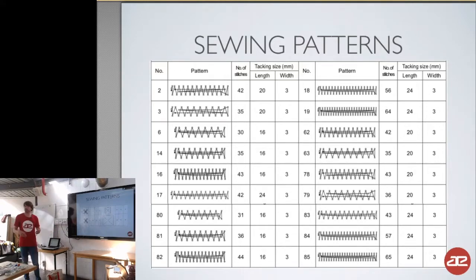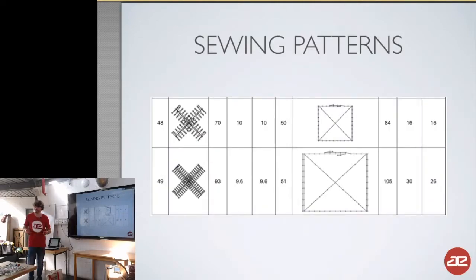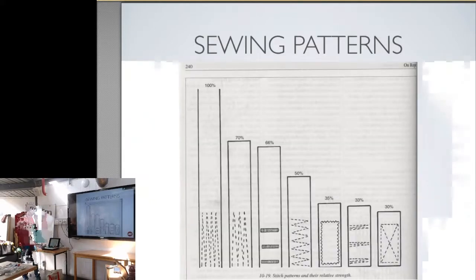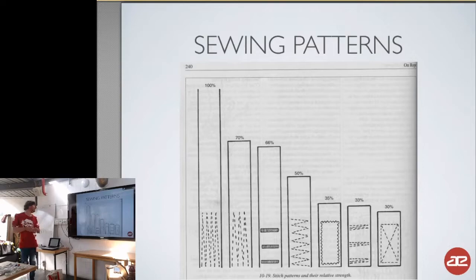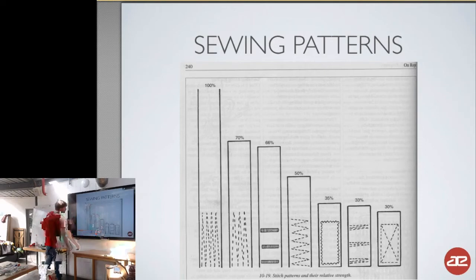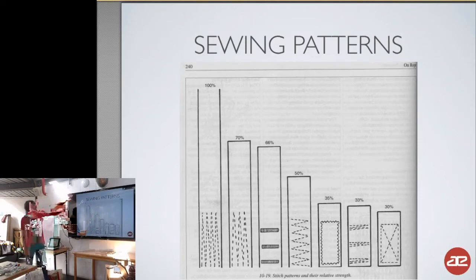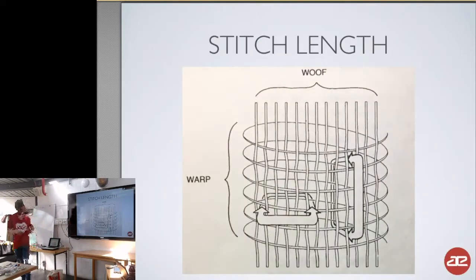So the topic of finding the right sewing pattern is a bit more complex than just sewing a bar tack with this yarn. In the literature on ropes some years ago, there was a graphic that compared the strength of certain sewing patterns to each other. You have box stitches or 3 bar tacks compared to a zigzag on the length axis sewn on a webbing. And they found already years ago that a pattern with a zigzag stitch on the length axis of the webbing possibly retains the most strength of any sewing pattern that can be sewn to a webbing.